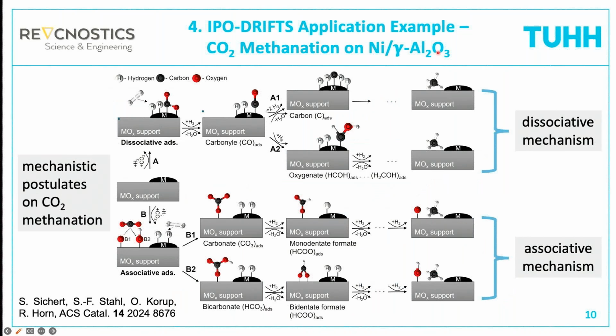And when we started this work, we first read the literature on how this reaction proceeds mechanistically. The catalysts that are used are typically metal nanoparticles on a metal oxide support. In our study, as I said, we chose nickel nanoparticles on a gamma alumina support. And there are now two schools of thought on the reaction mechanism. One group of researchers postulates that both the hydrogen and the CO2 adsorb on the nickel nanoparticle, and the CO2 dissociates upon adsorption. The hydrogen dissociates as well, but the CO2 also dissociates. So we get hydrogen atoms and we get adsorbed carbonyl species.